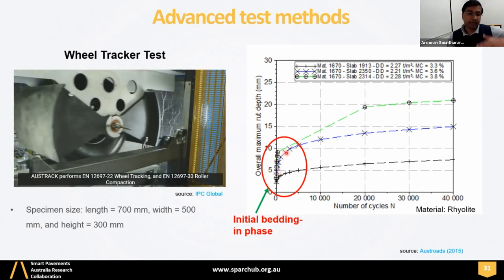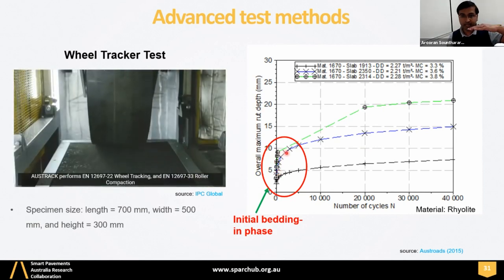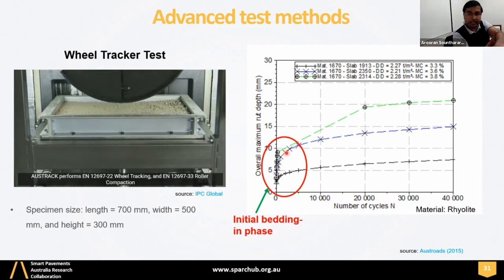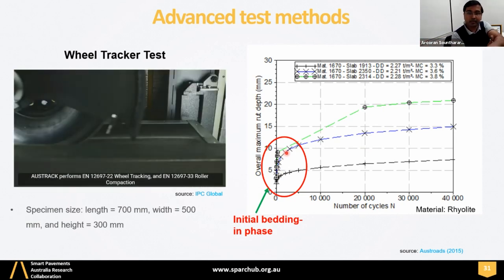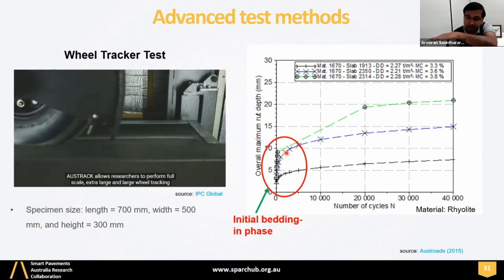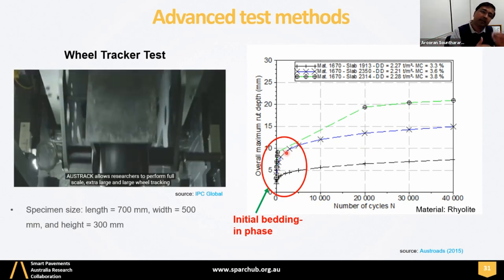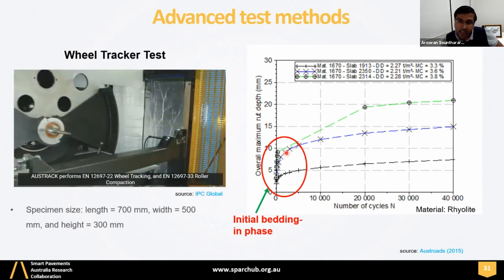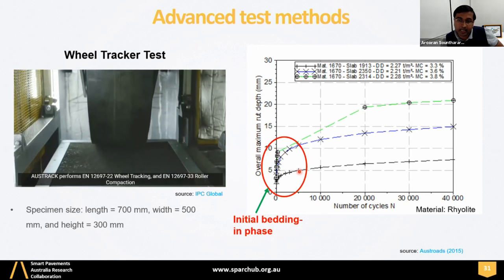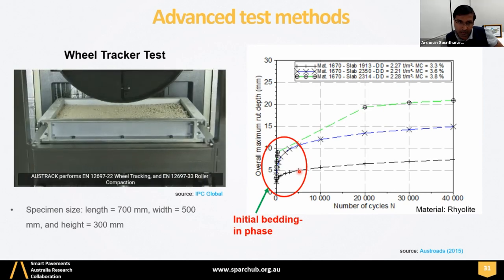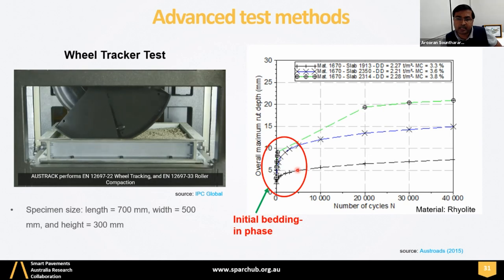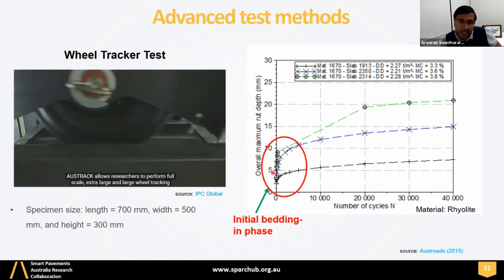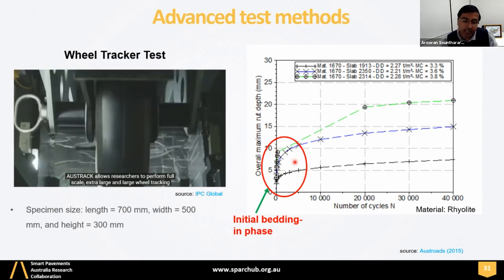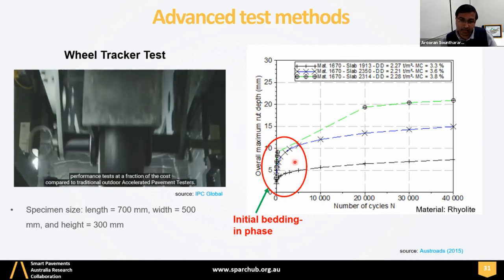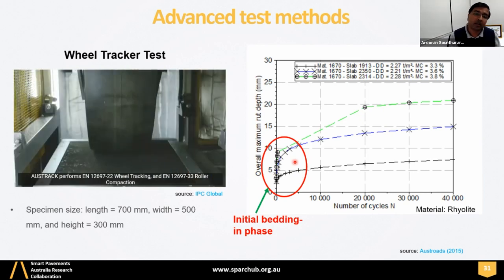Yeah, what you see here is rutting profile measured with the laser profilometers over this pavement slab. So they use a laser profilometer after every 10,000, 20,000 cycles to capture the surface profile, and then they back calculate the maximum rut depth from this, right? So this captures the rutting behavior of this certain crush rock in a field behavior manner, right? So initial rutting is always observed in the evaluation, which is the initial bedding-in phase as per our field evidence.